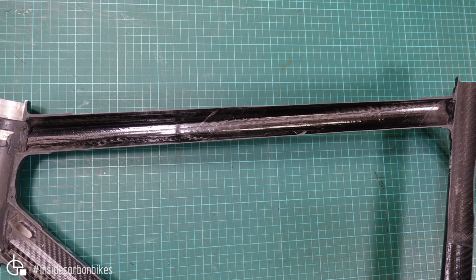So here's an overview of the top tube, and you can see that wrinkle that I was talking about in the previous slide goes all the way to about here. The other thing of note is these lines here, 45 degrees, that's all delamination. So the tube is delaminated through the thickness, and that's how these structures absorb energy. What is interesting though is that on the top tube you've got a unidirectional inner layer, whereas on the down tube and the seat tube it's a twill woven fabric, which is a little bit more forgiving from an energy absorption point of view, because of the mechanical interlocking of the fibers, so a bit less likely to delaminate.